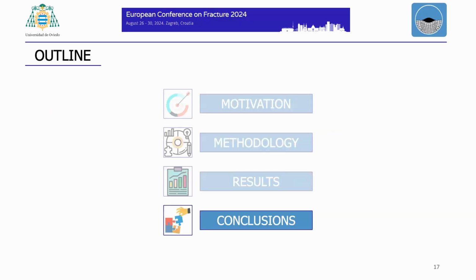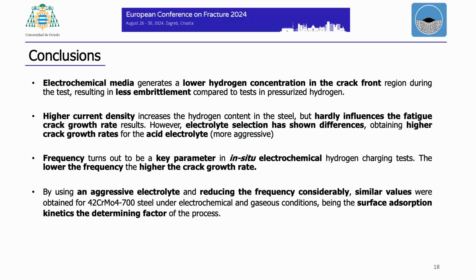So, conclusions, just to conclude. Electrochemical media generates a lower hydrogen concentration in the crack front region during the test, resulting in less embrittlement compared to tests in pressurized hydrogen. Higher current density increased the hydrogen content in the steel, but hardly influenced the fatigue crack growth rate results. However, electrolyte selection has some differences, obtaining higher crack growth rates for the acid electrolyte that is more aggressive. Frequency turns out to be a key parameter in in situ electrochemical hydrogen charging tests. The lower the frequency, the higher the crack growth rate.